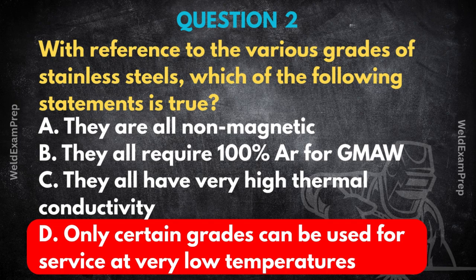Okay. And C, the high thermal conductivity. Yeah, this one's interesting because it's actually the opposite for the most common types. Really? Yeah, austenitic stainless steels, the ones used most widely, actually have lower thermal conductivity than regular carbon steel. Lower? Lower. And that can be a real headache during welding. It means heat doesn't dissipate as quickly, which can lead to more distortion if you don't manage it carefully. Okay, so that's A, B, and C debunked.